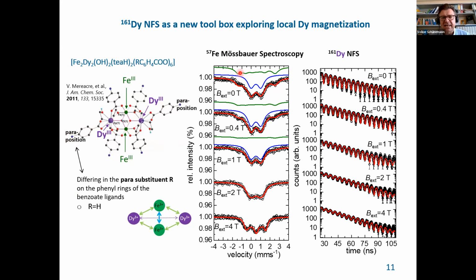And if you take these complexes, here we took the H-modified complex and measured that at 4.2 K in increasing field, that's conventional Mössbauer spectroscopy, this magnetic split part, 50% of the Mössbauer spectrum went away. And we were left over with a diamagnetic state here, which is 100% antiparallel coupled of the iron spins. And the dysprosium, on the other hand, these are data now measured at APS under exactly the same condition. There we could infer that the dysprosium just act as they were alone. They act as isolated dysprosium ions.